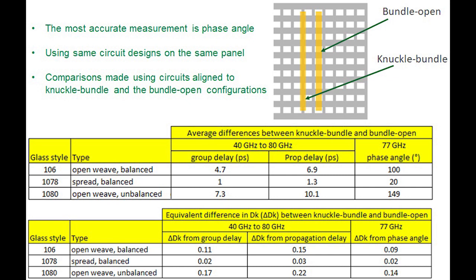Now, the next glass style, the 1078, that's the spread glass, and as you remember, there's no openings there. It does still have knuckles on one axis, but it is spread glass on the other axis. So you can see the glass weave effect is really minimized there, so the difference of these two different conductors using the 1078 glass is minimal. It's about 20 degrees phase angle at 77 gigahertz. And for the radar sensors, that's actually pretty tolerable. That's not a bad number.